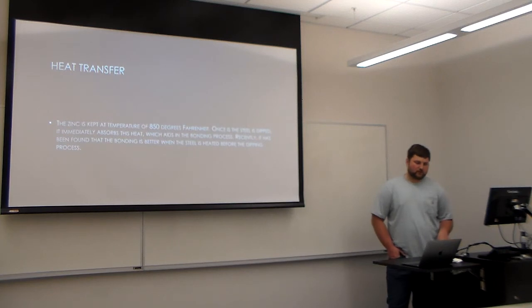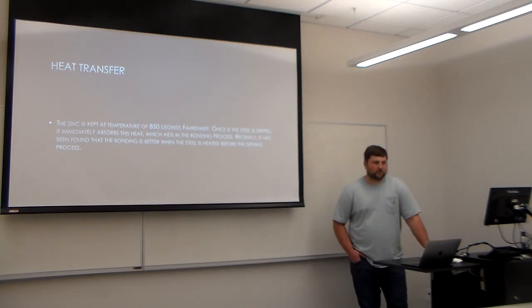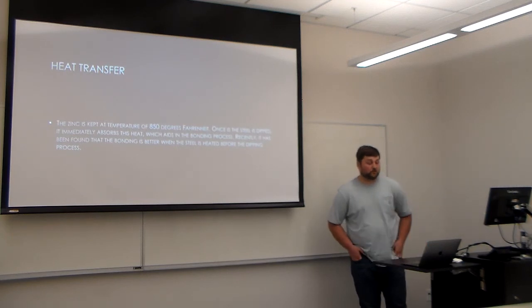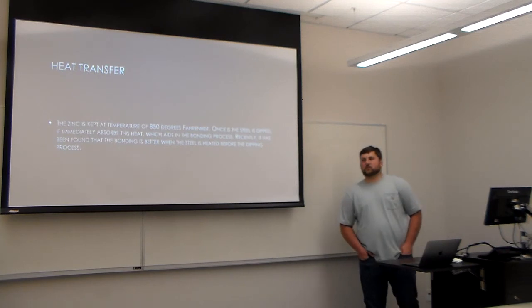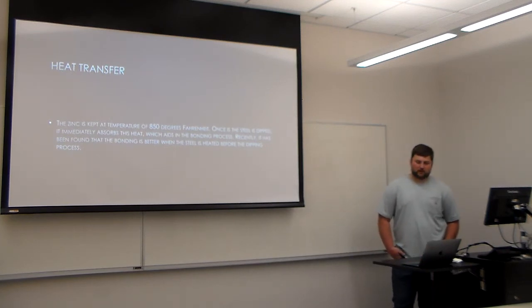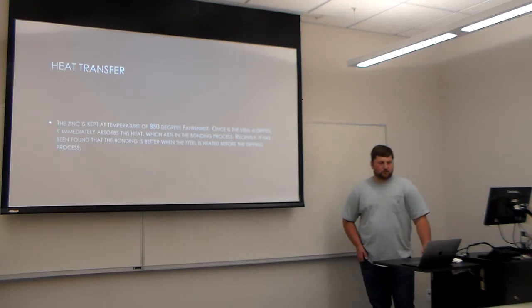So related to heat transfer, there's several aspects with the furnace itself, but I'm focusing on the dip of the product itself. The zinc is kept at 850 degrees, which sounds really hot, and it is. But when you think about it, it's four times as hot as boiling water. So that's kind of for perspective. Once the steel goes into the zinc, there's something known as flux that burns off and creates ash that floats to the top. You have to remove that. But really, once it gets down into the zinc, that steel sucks up all of that heat and the zinc starts to bond.